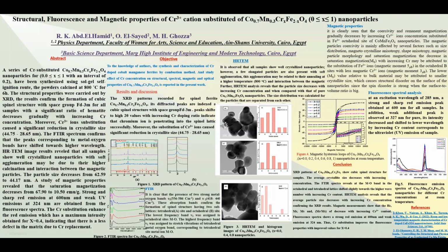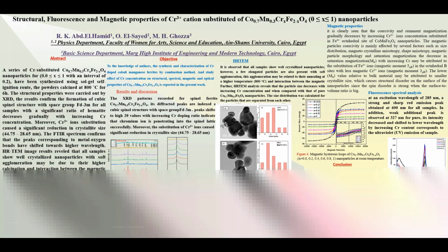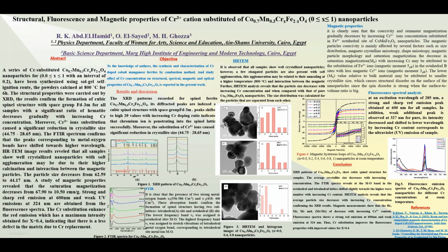In the present work, we prepared a series of chromium substituted cobalt, manganese, chromium ferrite nanoparticles from X equal 0 up to 1 with an interval 0.2 using a sol-gel self-ignition route method. The powder was calcinated at 800 degrees centigrade for 6 hours. The structural properties of the samples were carried out by XRD, FTIR, and high resolution transmission electron microscope.